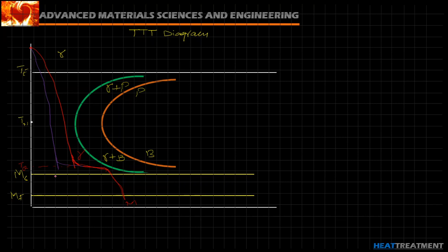So this time can be used to equalize the inside and the outside temperature of the component, and this is the idea behind Mar quenching or Mar tempering. And if we consider the inside and outside cooling curves before the start of the martensite, we interrupt the cooling before the start of the martensite.